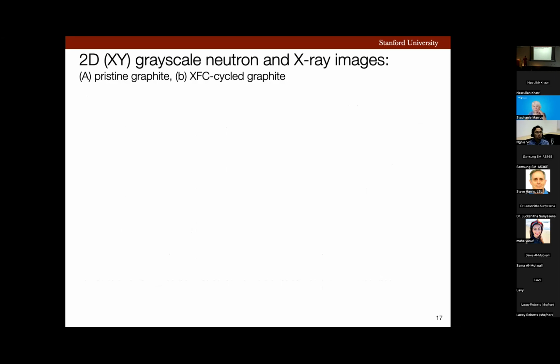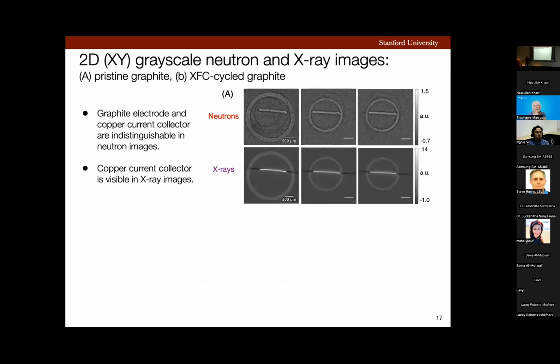Let's look at the 2D or top view or XY grayscale neutron and X-ray images of first the pristine graphite strip and second the XFC cycled strip. These are the neutron and X-ray images of pristine graphite. Here, the outer circle corresponds to the glass capillary that was used to house the sample. And in the neutron image, we can see one strip, which means we cannot differentiate between graphite and copper. But in the X-ray data, we can see this copper strip pretty clearly. This makes sense because X-rays are more attenuating to high Z materials, such as copper. In addition, we can see these dark streaks coming off the end of the copper, which are beam hardening artifacts.